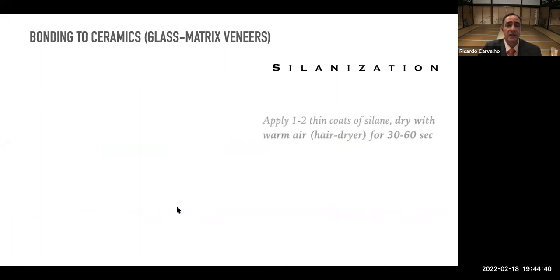Silanization is a highly important aspect here because that's when we're going to accomplish the chemical bonding to the ceramic surface. So we already have the porosity to increase our micromechanical retention, but we also want to stabilize that bond by a chemical adhesion to the ceramic surface. And as we know, silane is exactly this coupling agent which will allow for the chemical bonding between the ceramic particles and the resin matrix.